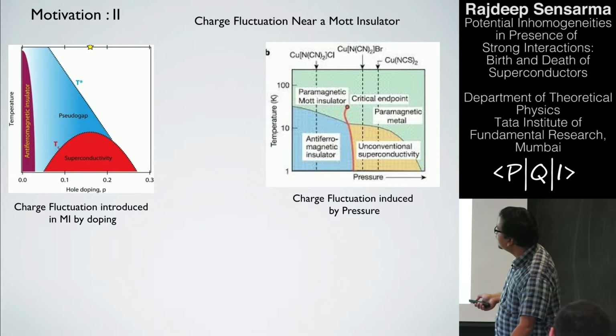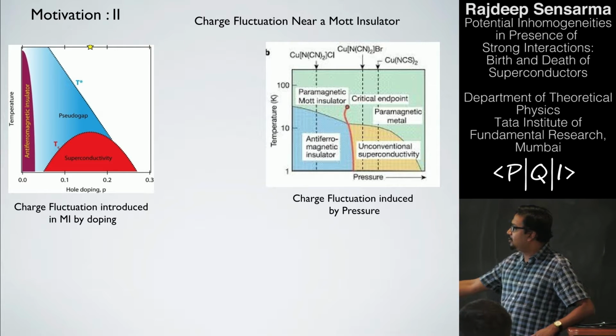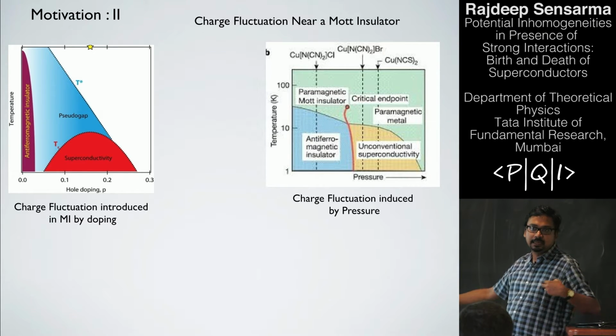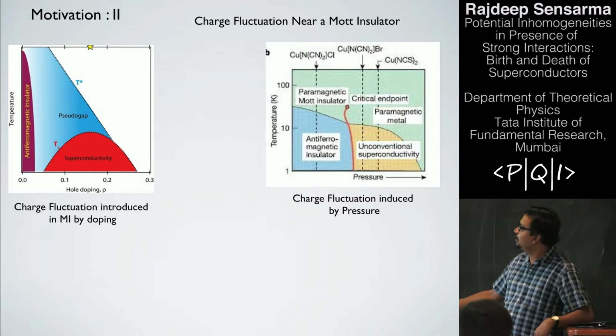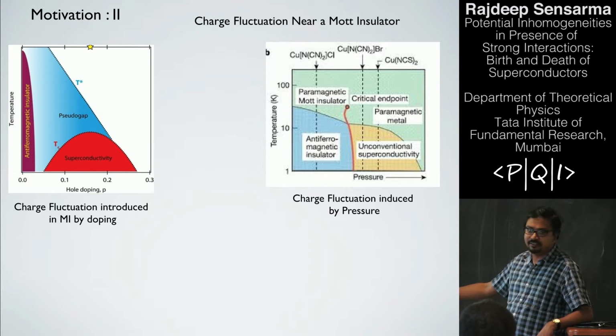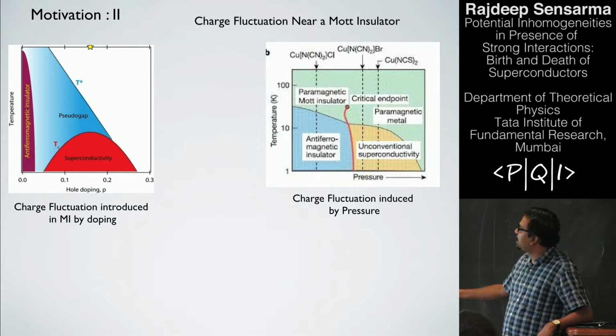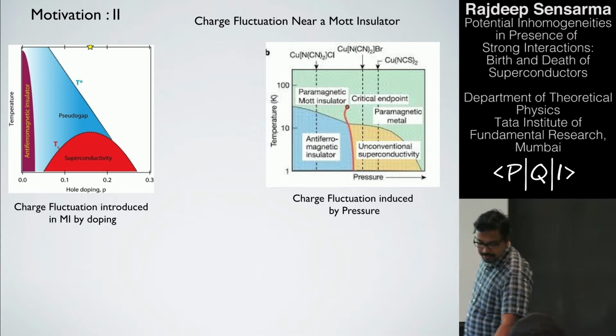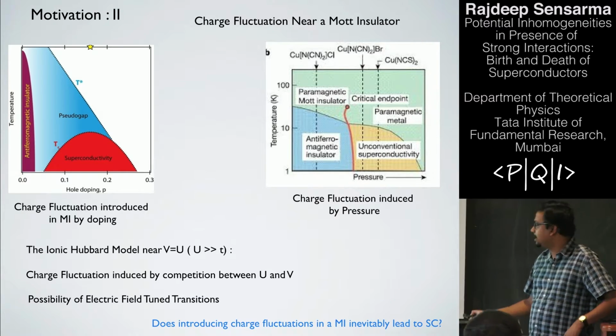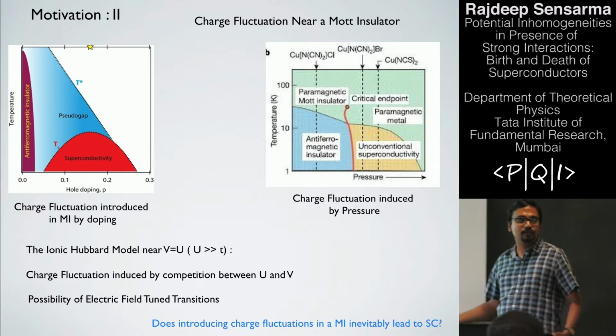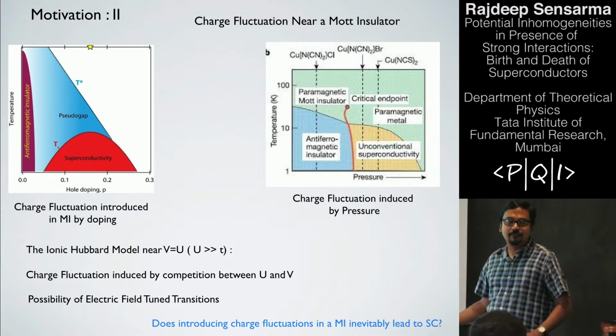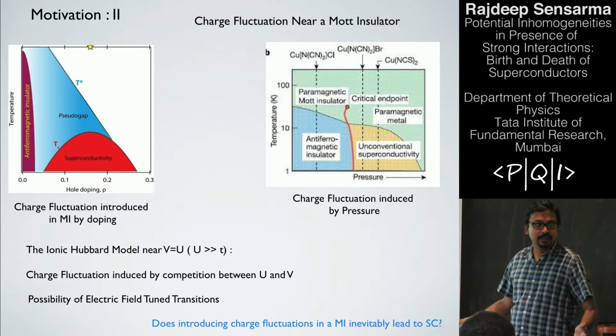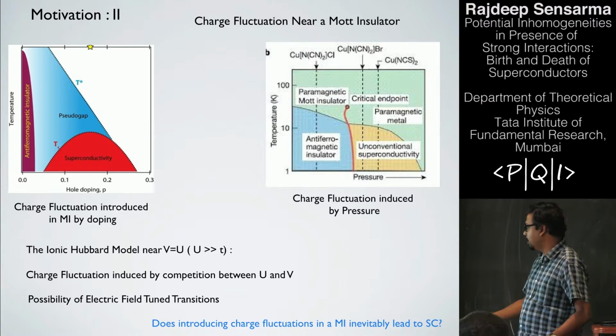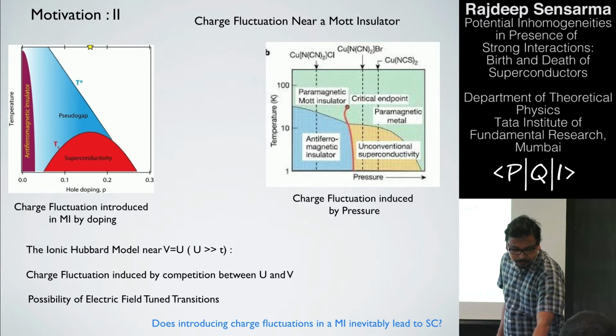Motivation 2 is that we have seen in this case at zero doping there was no charge motion. As you allow charge to fluctuate around the Mott insulator, you suddenly get superconductivity and a host of other interesting phases. This is another material, which is called organics. Here things are tuned with pressure. But again, as you start allowing charge fluctuations around the Mott insulator, you start getting superconducting states. And in fact, you can ask, is this kind of a fait accompli? Does introducing charge fluctuations around the Mott insulator always lead to superconductors? And is this then a good way to always think about getting higher and higher temperature superconductors? So that's the kind of question you can ask here.